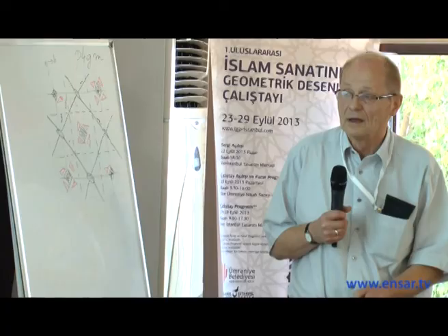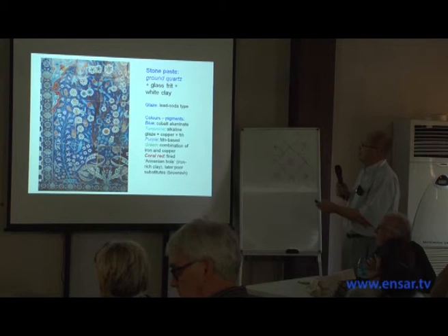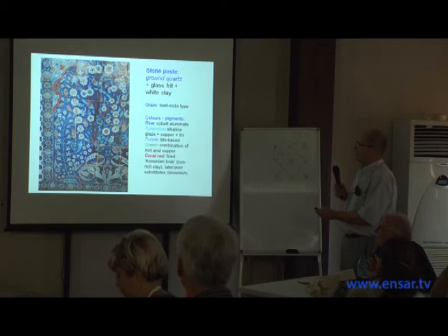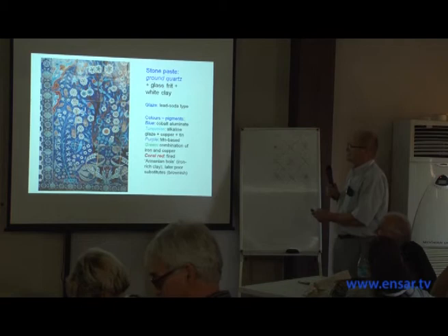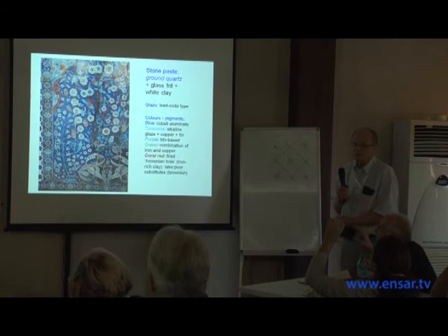We better go. So here, the blue, okay, the glaze of stone, the ceramic made of ground quartz, ground glass of special composition, and a bit of white clay, and that was fired to be a brick. Glaze was, of course, silica, but with some soda, which is sodium, natrium, and always lead compounds. So don't eat from Iznik ceramics.